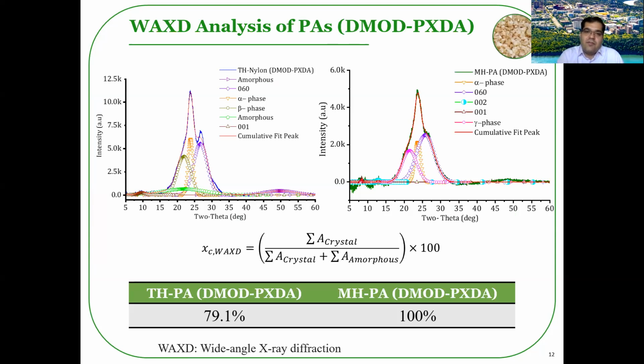The crystalline structure of the semi-aromatic polyamides DMOD-PXDA was analyzed using wide-angle X-ray diffraction analysis. As you can see, the deconvoluted peaks of the semi-aromatic polyamides were produced under different heating processes. Traditional polycondensation encouraged the polyamides with higher diversity in the crystalline phases, while the microwave irradiation produced polyamides having gamma phases but not the amorphous phases.